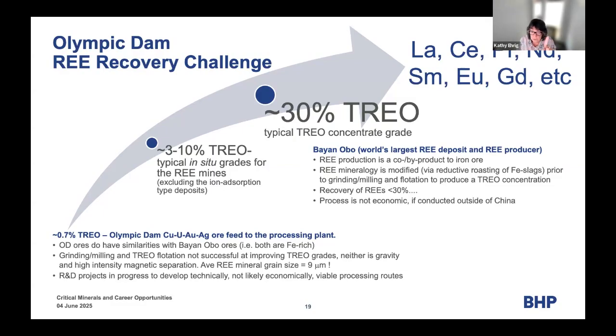The first thing we've got to do, particularly on the research side, is what's technically possible. Economics is something applied after you come out with a viable processing stream. And we think for a minute, what can we learn from Bayan Obo, that their rare earth production is a co-byproduct of iron ore production. Their rare earth mineralogy is actually modified by reductive roasting in the production of the slags, and so they take slag from their iron ore process, do a reductive roast, control the cooling rate, which allows monazite to grow in size big enough that it becomes amenable to grinding, milling, and flotation to produce their rare earth concentrate.